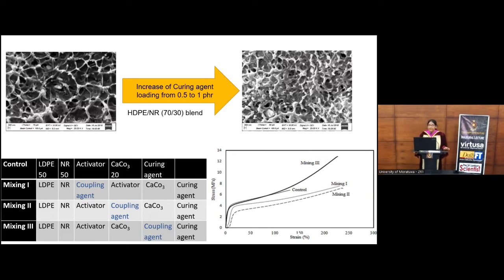Another thing, we can enhance the adhesion or the cohesion by changing the mixing order. Here you can see a control, that means without adding any coupling agent, but when we add the coupling agent, we can reinforce the polymer blend, and the mixing order will give different properties suitable for different applications.